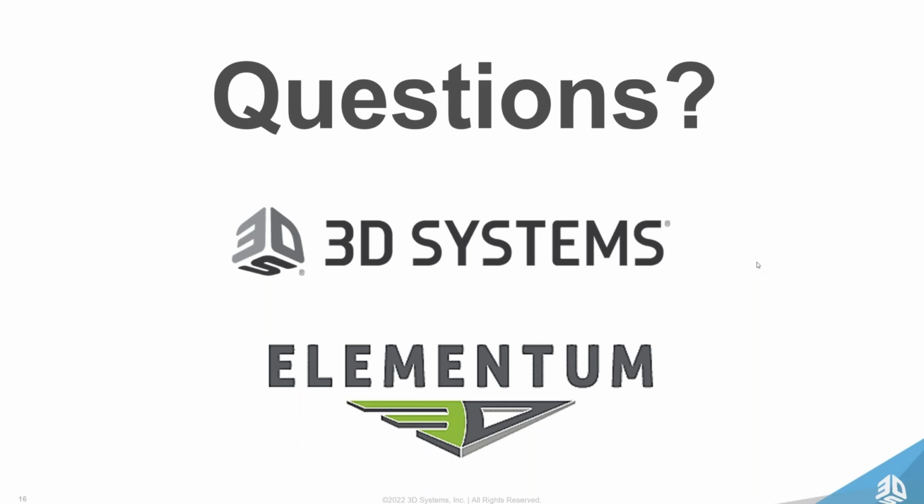Great, thank you. Next question is, does 6061 experience any marked increase in properties from hot isostatic pressing? Now, for certain customers, certainly HIP is the preferred method, and we do have customers that are doing HIP to the material. We don't really find a big increase in strength or anything like that, and we haven't fully studied fatigue in the HIPped condition. So I think fatigue would be the interesting one to look at there. We get great fatigue performance without the HIP, but perhaps it's even better with the HIP. We're not sure yet.